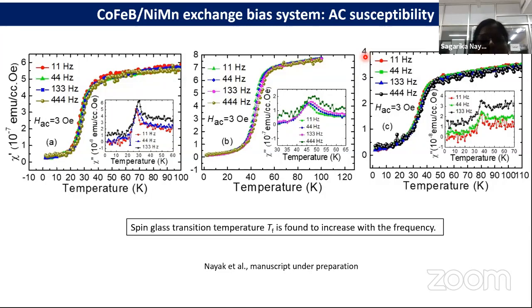Again, to know whether there is a role of nickel manganese, and whether it is spin glass or not, we performed AC susceptibility measurements, and we found that a phase transition is present in all the plots, and this temperature TF shifted to higher temperature with increase in frequency, indicating that yes, there is a role of spin frustration in the system.